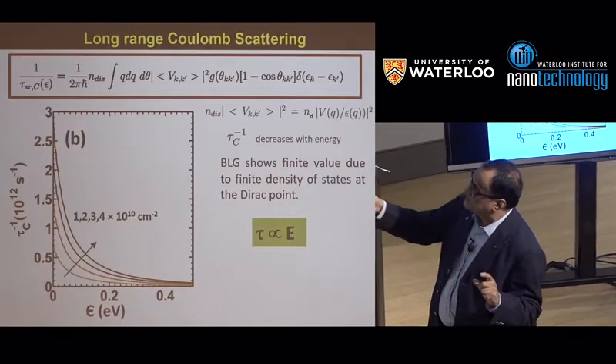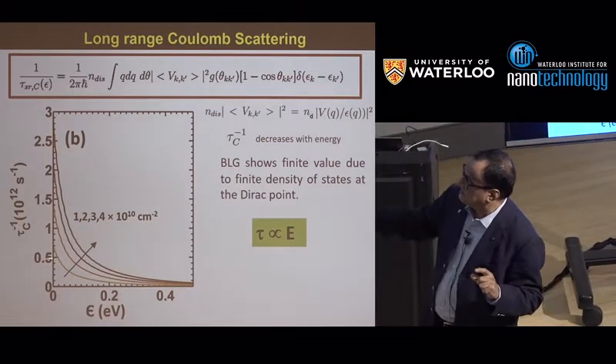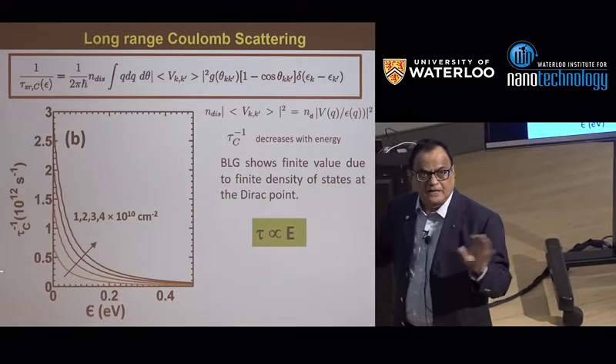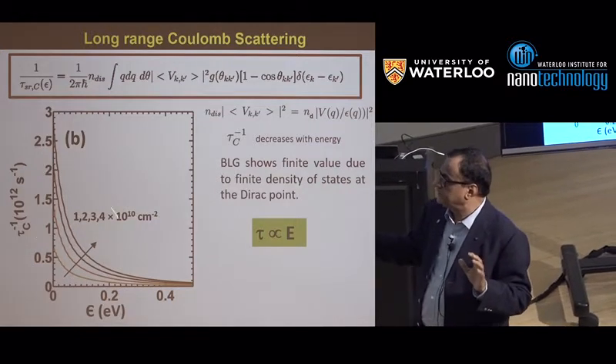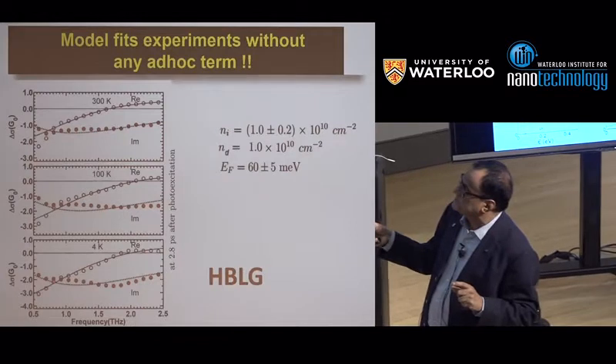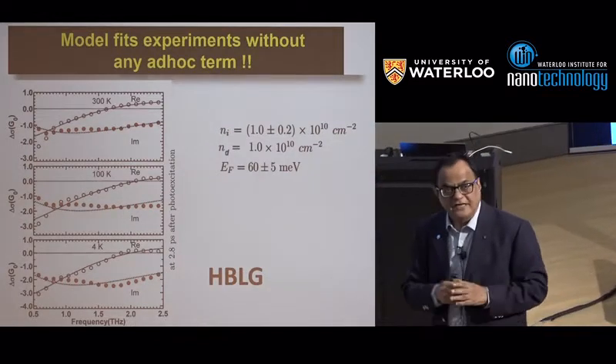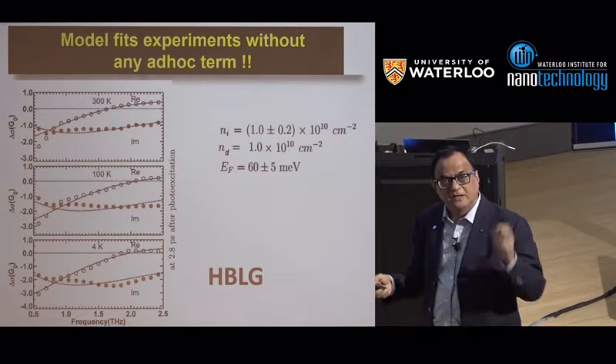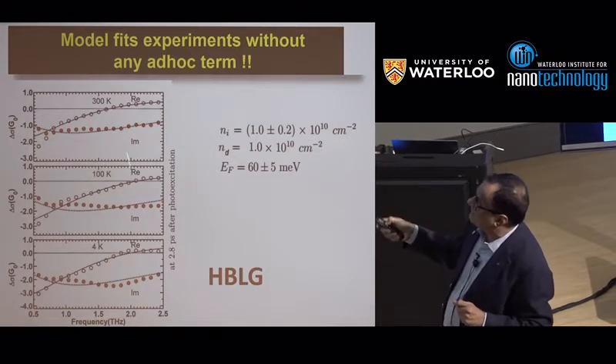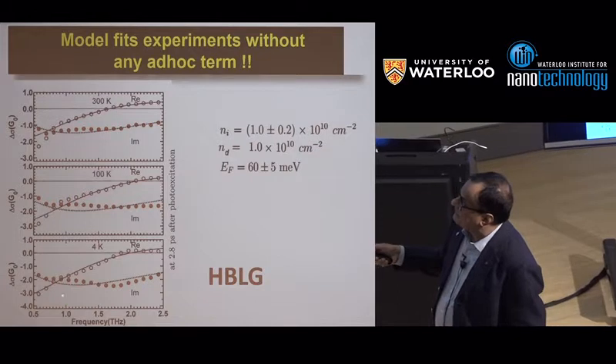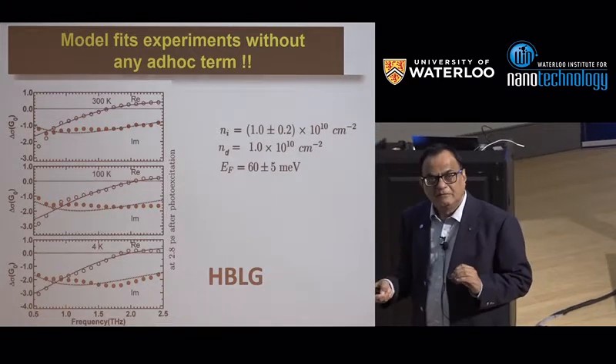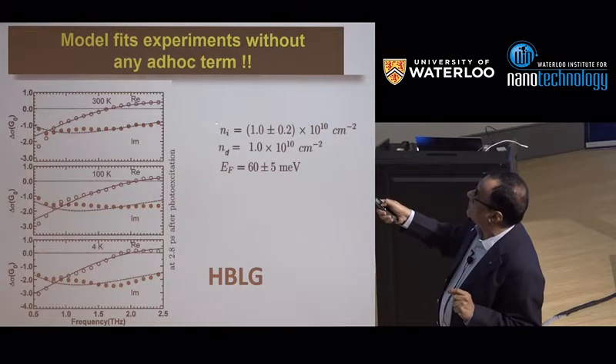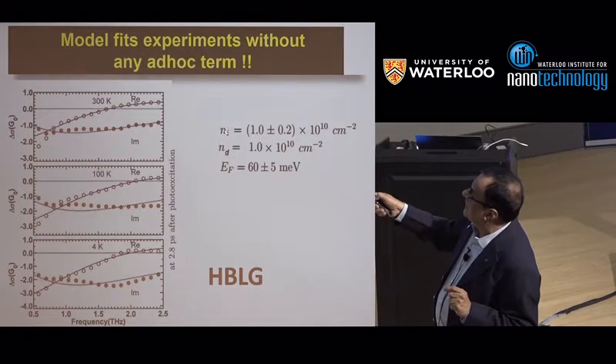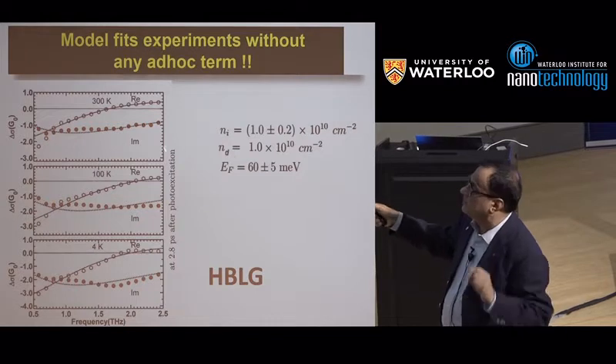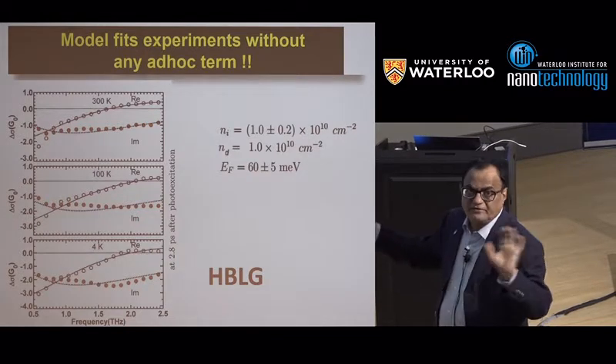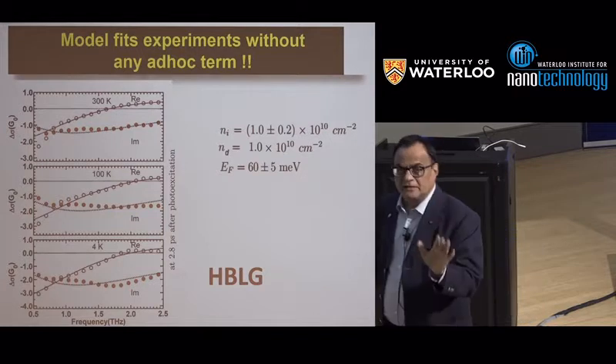We do all this energy dependence, which is quantitative. This is not arbitrary scaling. It really has to be seen whether this is correct. We put all these mechanisms, and lo and behold, at the end of the day, you do those integrations, do the evaluation at different electronic temperatures and lattice temperatures, and the experimental data fits extremely well. If you fix these impurity concentrations and the oscillator strength, the V naught, for one temperature, nothing has to be varied after that, and everything gets explained.